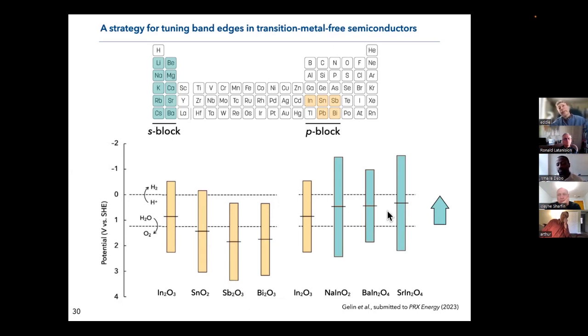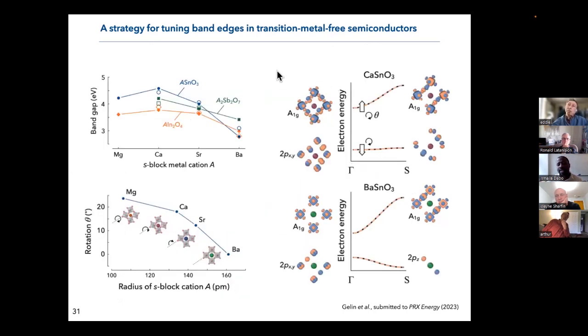But we're also surprised because if now you mix S block elements that are very electropositive with these electronegative elements, you might make the material more ionic, more salty, meaning that they're essentially more transparent. And the expectation will be that those materials will not be so good light absorbers. So the question is, why is this the case? How come that we can still absorb solar light? And it all has to do with the distortion that are induced with the size of the cations that we have in the lattice.